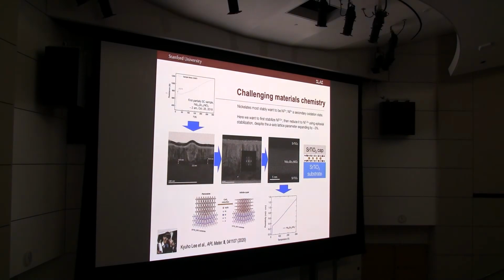So really, probably the most important thing that we had been doing on this problem is trying to understand this rather challenging materials chemistry problem. As I already told you, nickel has these preferred oxidation states, and we want to do something rather peculiar, actually. What we're trying to do is to hole dope the system. So we hole dope the perovskite phase by chemical substitution to a very extremely high oxidation state and then reduce it to a very low oxidation state.